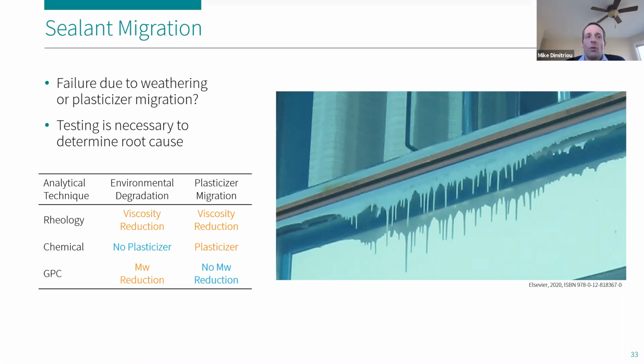So what you require in situations like this is some form of testing to figure out what is going on. So you can deconstruct these windows, harvest this sealant, and perform a number of tests to determine what is the root cause. So I've broken it up into kind of three simple concepts here. What you can see both visually, but through some sort of rheological testing, is that this material is showing a reduction in viscosity. And this can be caused by both environmental degradation or plasticizer migration.